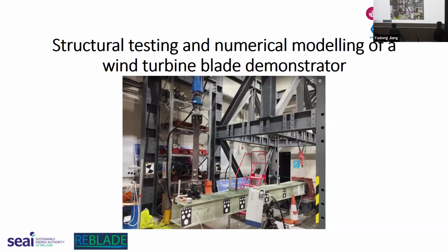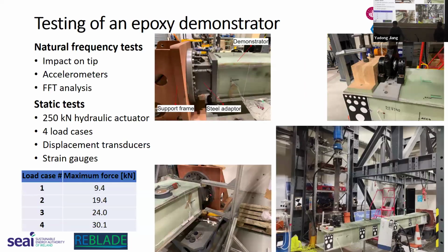Okay, just to mention, Conor presented the manufacturing of the two demonstrators, but the real timeline is that he first manufactured the epoxy demonstrator, then it was brought to our lab for some testing. Then we found some aspects that we could improve. Then we manufactured the second demonstrator, the Elium one, to test and see if this type of recyclable composite material will be suitable for manufacturing large-scale composite structures like wind turbine blades. So here I will present the testing of the epoxy demonstrator first.